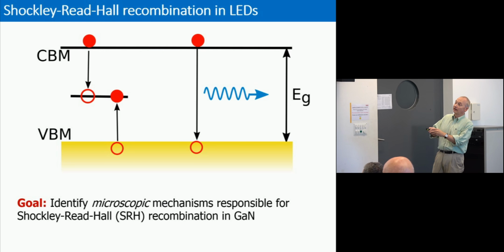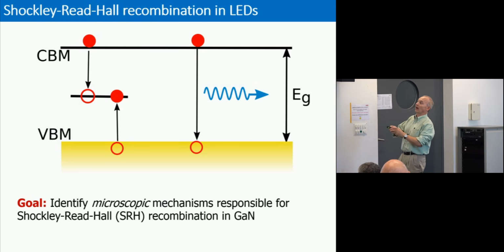And then subsequently it can drop down the other energy by recombining with a hole, or alternatively you could say, well, once an electron is sitting on the defect level, you're actually capturing a hole. Remember, holes like to bubble up in these sorts of energy diagrams. You capture a hole, and that constitutes a full recombination cycle in which you basically lose an electron and a hole.